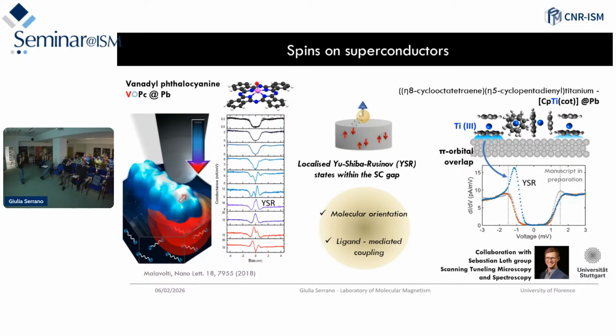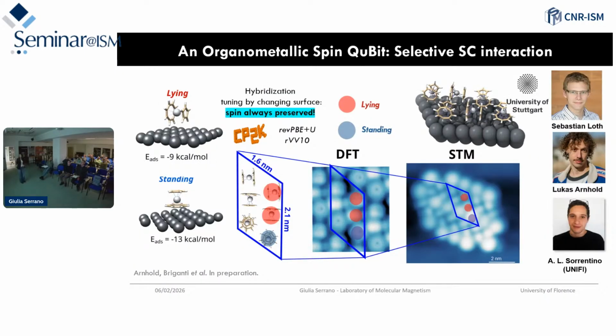view, because as I mentioned at the beginning, as soon as we can couple a single spin with a superconductor, with the Cooper pair of the superconductor, if this coupling is effective, we can then produce a localized bound state that appears in the spectroscopy within the band gap of the superconductor. So this is a collaborative research that we have with the group of Sebastian Loth in Stuttgart, which does low temperature or very low temperature STM. And on this kind of molecule, CpTiCOT deposited on the Pb(111) surface, we saw again that we had some rafts in which we had standing and lying-oriented molecules.